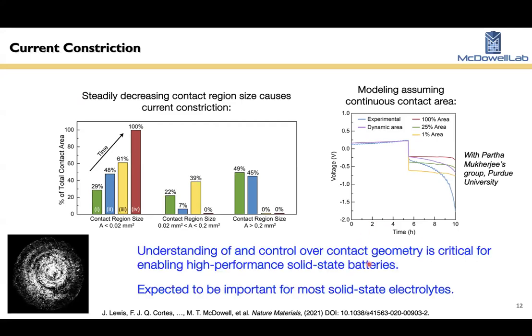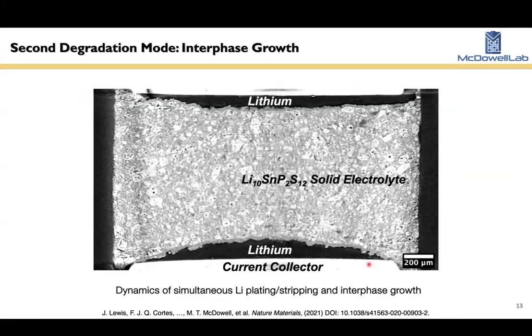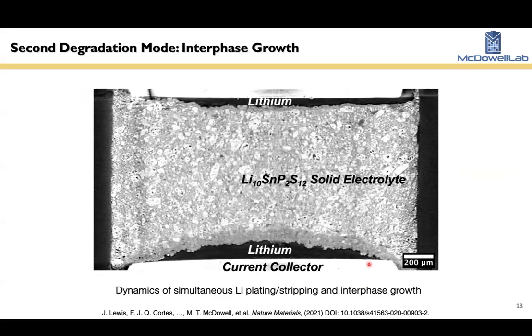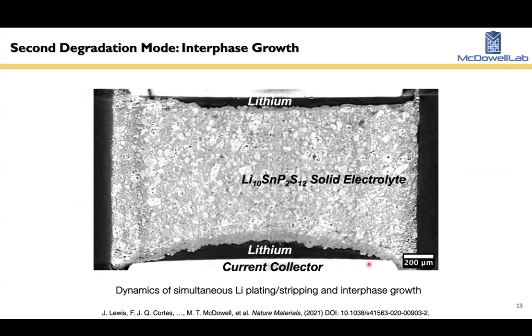These current constrictions are a problem. They can cause filaments to form when you charge the cell. And this is the first time that anyone had measured these sorts of contact evolutions in these batteries. So this can be applied to any sort of solid state battery chemistry. It's important to understand how contact evolves during stripping. Okay, so that's contact loss, very big problem in solid state batteries.